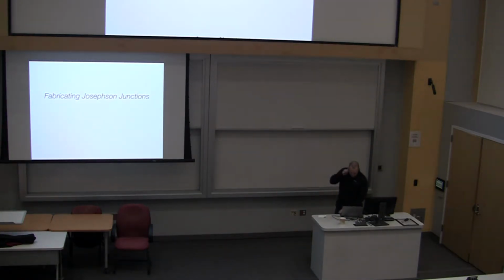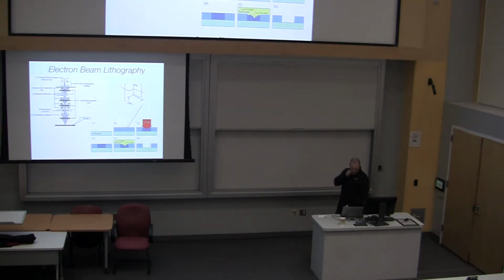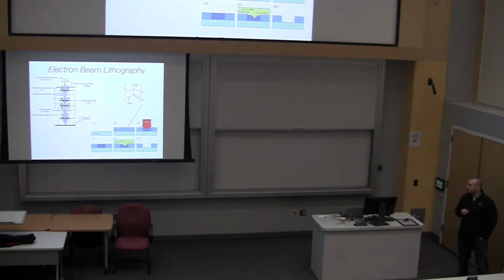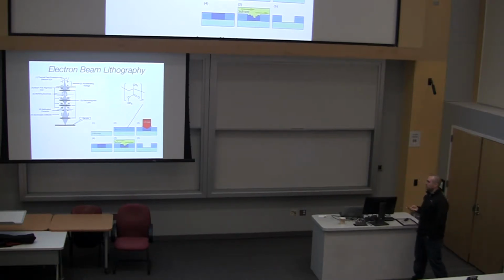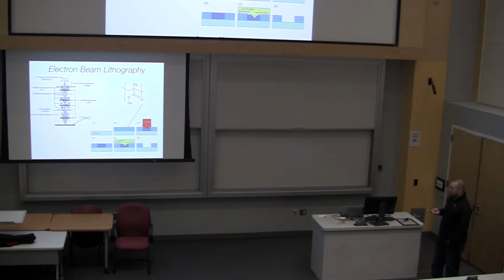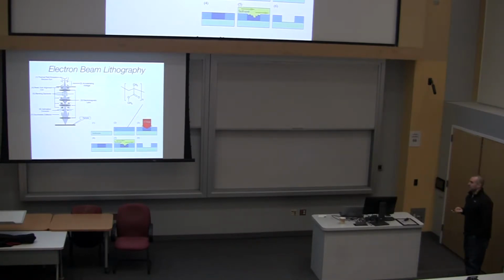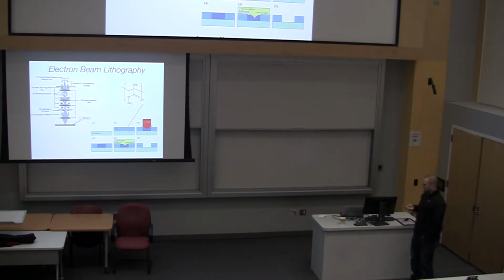So to start, I'll just talk about how we fabricate these junctions. One of the practicals was on e-beam lithography. What happens in e-beam lithography is electrons are collected off of some filament and accelerated to high voltages. I'll talk in a little bit about what those high voltages actually do and why they're important. This beam of electrons is diffracted through a combination of electrical and magnetic lenses, and then are focused down onto the sample.